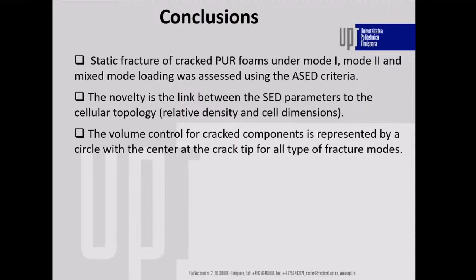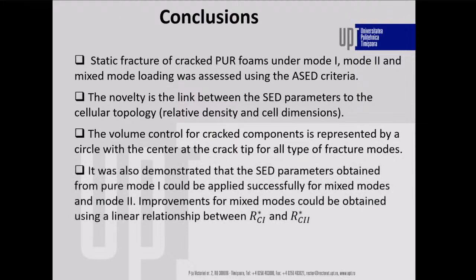The volume control for cracked components was represented by a circle with the center at the crack tip for all types of fracture modes. And it was demonstrated that the SED parameters obtained from pure mode 1 could be applied successfully for mode 2. But if you want to improve the predictions of the maximum load, we use a linear relationship between the control radius determined with the properties from mode 1 and with the properties for mode 2.